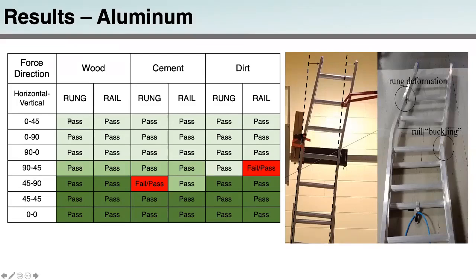So you can see here, the first set of testing in the light green here was all completed on one ladder. We then had a very short duration where the second ladder we used was exposed to impacts, and then from that it failed again, and then this darker green shows a separate ladder that we use, a third ladder that we used to finish off the testing. Following failure, as I previously described, a new ladder was used to retest the conditions. Both failed conditions passed upon retest, and the initial failure was determined to be cumulative fatigue failure.